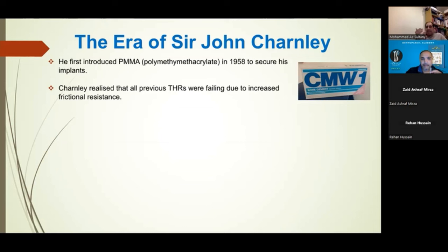He then realized that to get longevity and survivorship of a hip replacement, you need to have an environment where there was very low frictional resistance and wear in the surfaces that were moving, so the bearing surfaces. So you had to have effortless motion between the two surfaces, so that with less friction, you're less likely to get particulate debris, wear of the surfaces, and therefore failure. So with increased durability, the longer these surfaces last, the longer your replacement will last.